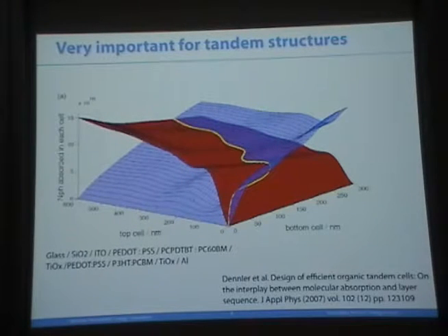This is a very convoluted pathway where you can either choose like 150 here and only 100 there, or basically similar further. In this thing, you can also see there's a problem here, of course, that what is assumed is basically that each photon that you absorb in each cell actually leads to current. Now, in a real device, that is not true, because if you make a really thick device, you can imagine, you make a device with several microns thick, then no charge carrier is actually going to arrive, because there is so much recombination at that point that it doesn't work. So what you really want to do